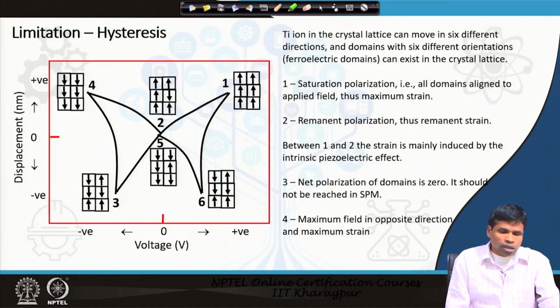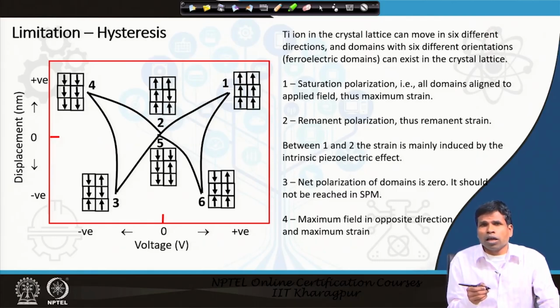So, now these domains have an internal electric field. If the internal electric field of the domains is parallel to the applied electric field, then that will be in the lower energy state. If the inner field of those domains is anti-parallel to the applied field, then they will be in the higher energy state. So, these domains would like to stay in the lower energy state, and therefore, they would like to reorient themselves parallel to the applied field. However, there is a barrier, they have to cross that energetic barrier to go from higher energy states to lower energy states, and